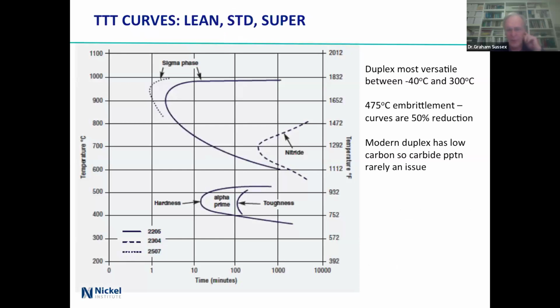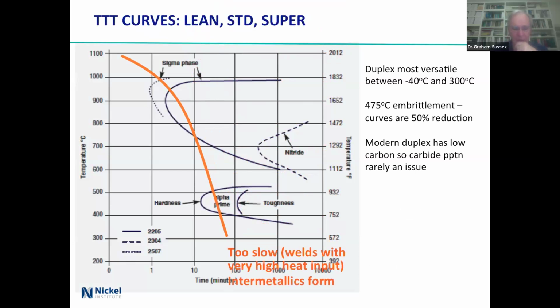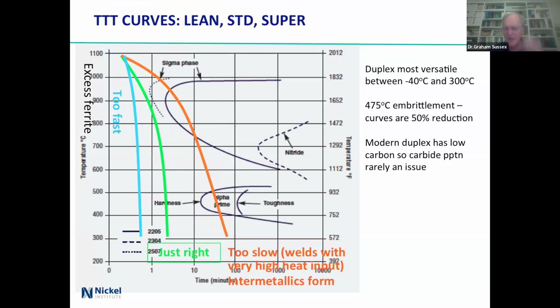Okay, so what's happening here? We saw this picture before. Sigma phase forming up there. We're cooling down slowly. Oh dear. Down there we wind up with sigma phase. Not good. We'll also wind up with a problem with the alpha prime. I did say before that at the bottom here, we've got 50% change at these for toughness and hardness. So let's cool it fast. Oops, that's much too fast. Excess ferrite. No, not good. And that's about right. So it's like Goldilocks and the Three Bears, for those of you who had Enid Blyton stories.